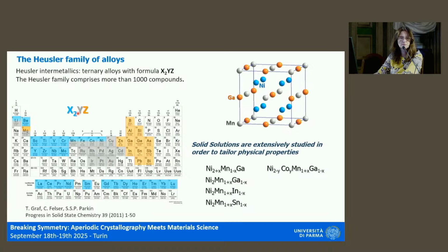The classical stoichiometry is the ratio 2:1:1, but we can find many other materials with off-stoichiometric composition, because in this way it is possible to tailor the characteristic temperatures of the solid-state transitions, the magnetic properties, and so on. One of the most studied and investigated materials is nickel-2 manganese gallium. We will see many results corresponding to this milestone of the Heusler alloys, and also other compositional variations around the nickel-manganese-gallium composition.